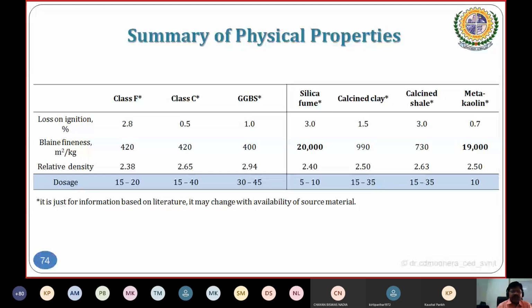Here loss on ignition is also not crossing more than 3%, so that is fine. Blaine fineness is also shown higher only for silica fume as well as metakaolin. Relative density is also more or less in a similar range. Only lower is silica fume or otherwise class F fly ash. And the dosage is already mentioned; the range is basically between 15 to 20. People have worked, a few are getting 17, a few 18.5, 20.